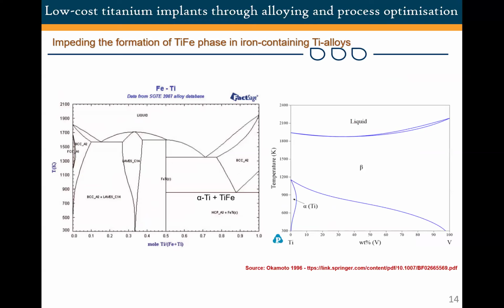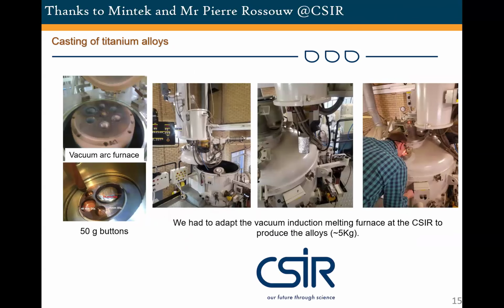And the reason for that is vanadium diffusion is quite slower compared to that of iron in titanium. And then that can mitigate the evolution of TiFe intermetallic compounds. So we had that theory at the back of our mind that with the partial substitution, we should be able to suppress the formation of that TiFe intermetallic compound, but we don't know how that will influence the mechanical properties. Would we be able to produce the alloy in the first place?